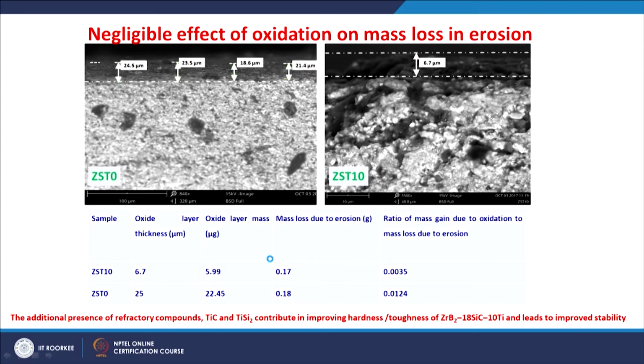Let us also understand the effect of oxidation on the mass loss in erosion. Very carefully the samples were flattened to see the oxidation layer thickness. So, for ZsT10, the maximum thickness of this oxide layer is around 7 micrometer, whereas for ZsT0 the maximum thickness is around 25 micrometer. You can see the ratio of mass gain due to oxidation to the mass loss due to erosion is very less: 0.0035 for the ZsT10 and 0.0124 for ZsT0. So, that means a very negligible effect of the oxidation on the mass loss due to erosion. The mass gain due to oxidation is negligible when you compare with the mass loss due to erosion. That means, we can say the material is removed by the mass loss during erosion significantly.